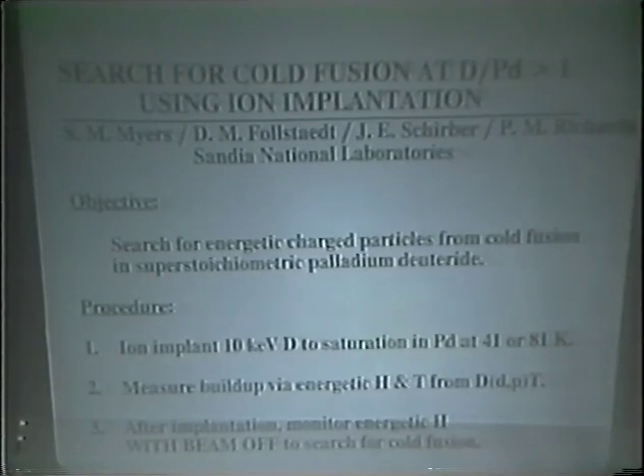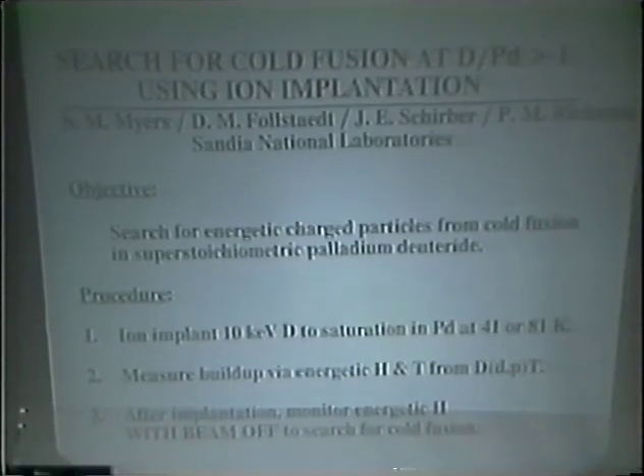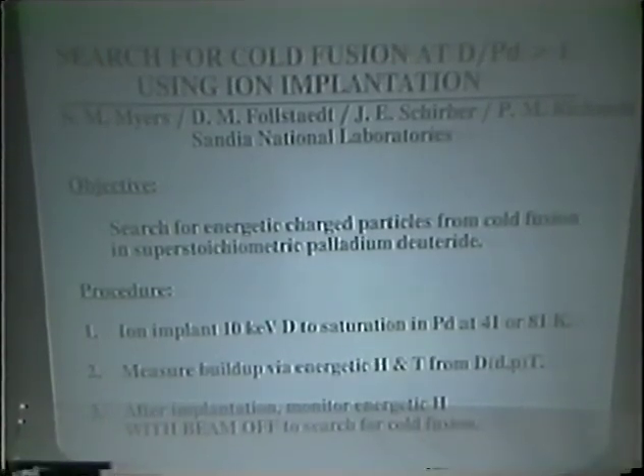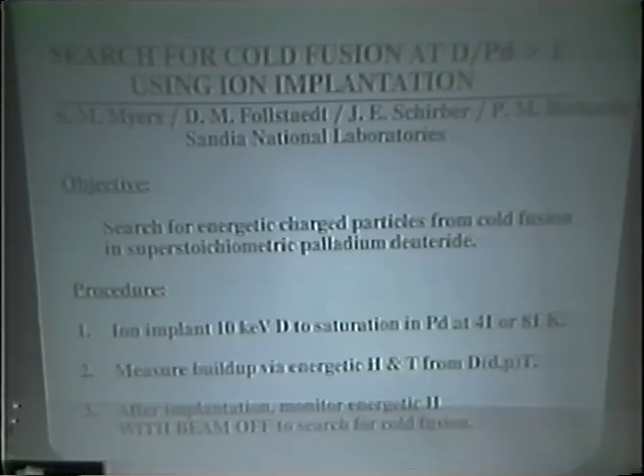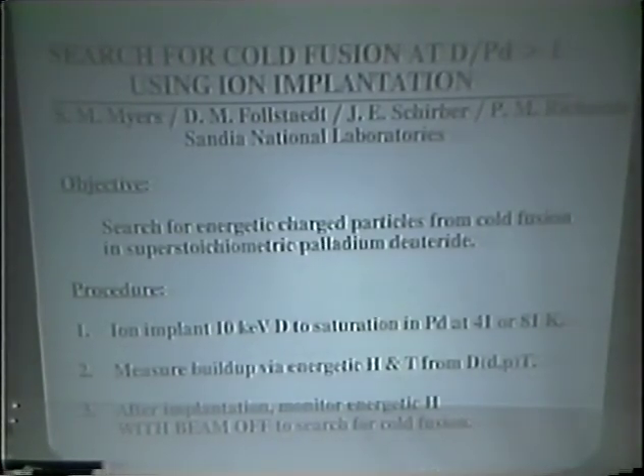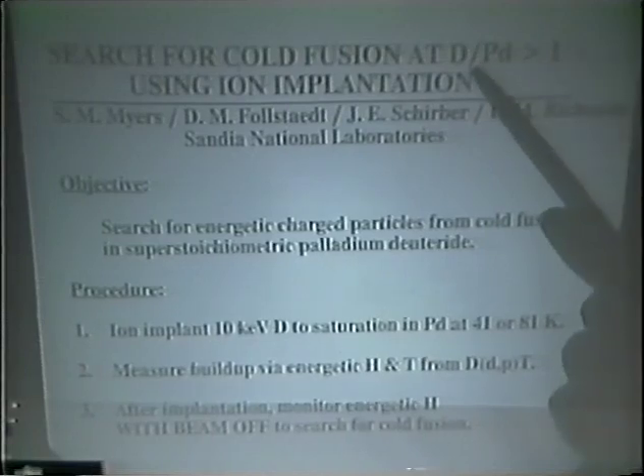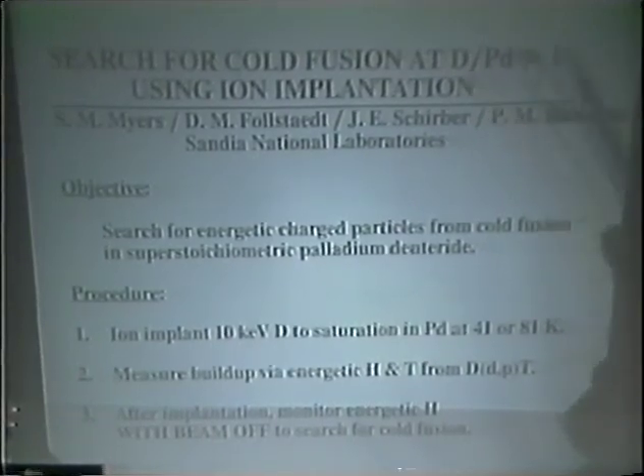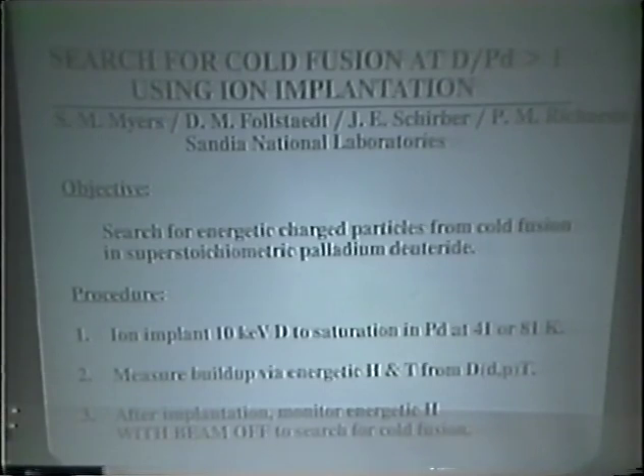As a matter of fact, the saturation behavior of implanted deuterium in palladium at cryogenic temperatures was investigated about a decade ago by Muller, Bessenbacher, the previous speaker, and Bödiger at the University of Aarhus. Using very detailed nuclear reaction profiling methods, they found that if you implant to saturation at low temperatures, the key being that the deuterium diffusivity is very small, so it isn't mobile once you inject it into the lattice, one reaches atom ratios of about 1.3 to 1.